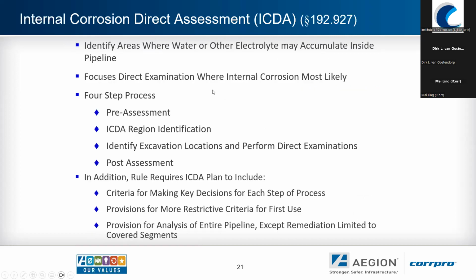So one of the first things we're looking at is a reference at top to 192.927. So that is a direct piece out of the federal regulations, which sets out some of the requirements for how one needs to assess the internal corrosion on the pipeline. So the first thing we're looking for are areas along this particular pipeline that's under study where water or any other electrolyte may accumulate. This can be water that's trapped in the flow stream itself. It can be water that forms due to condensation.